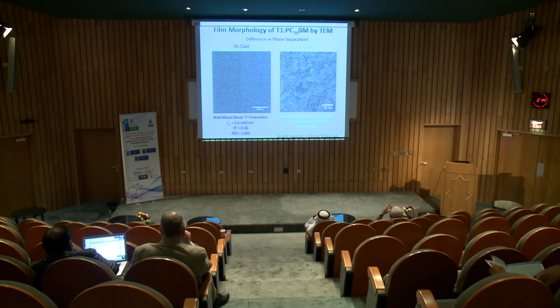We can also map out film morphology using transmission electron microscopy. You can see on the left-hand side for the as-cast, you don't see any features there. What that really means is that the donor and the acceptor blend really well. There is no contrast whatsoever. But if you go to the image on the right-hand side, which is the 0.4% DIO processed blend, now you can see beautiful crystalline domains appear throughout the film.